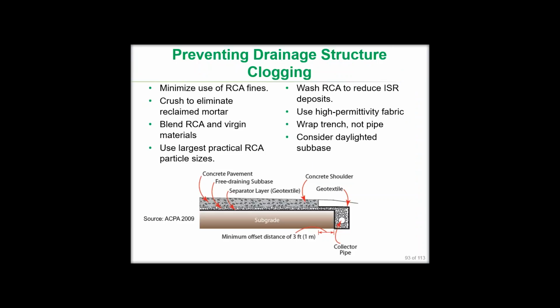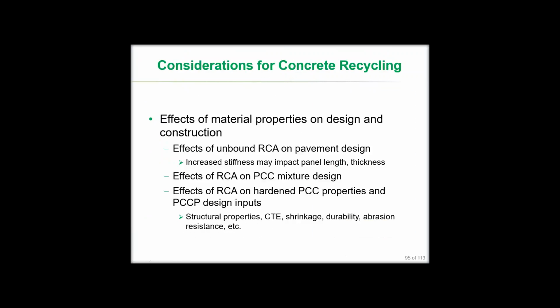Going back to the drainage issues for the clogging of the drain pipes, there are a number of approaches, and these have been outlined in an ACPA document, an engineering bulletin from ACPA on concrete recycling for pavements, and those are listed here. They include not only ways to reduce the amount of material coming from the aggregate, such as not using fine materials which have a higher surface area, and eliminating as much mortar as you can and blending with the aggregates, but also using high permittivity fabrics and things that are less subject to clogging, and wrapping the trench and not the pipe so that the water flows into the pipe and doesn't plug up on fabric that's placed around the pipe. Also the use of daylighted subbases. So there are a lot of different approaches there that can be considered.